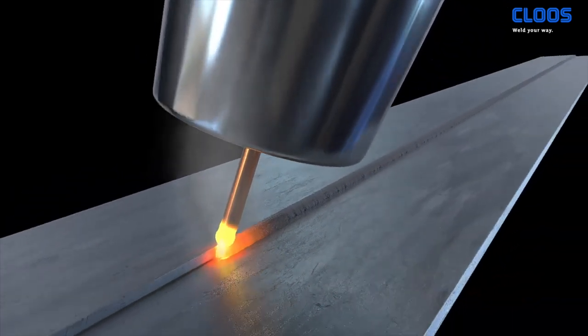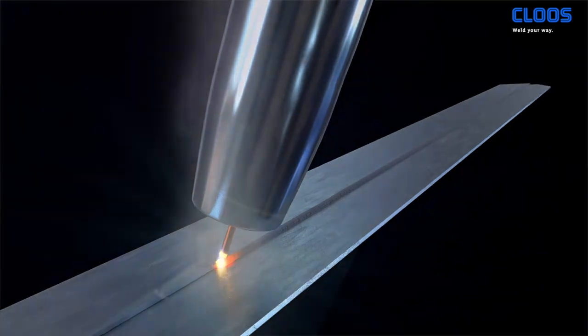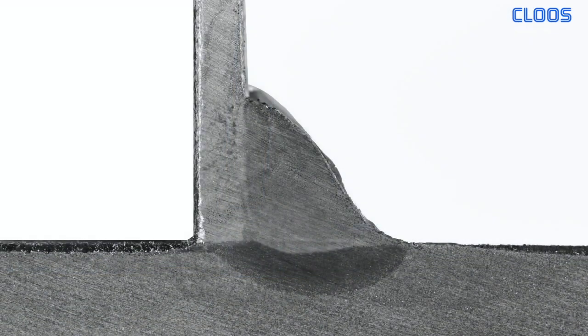The short circuit current, which is then significantly increased to generate the pinch effect, is very quickly reduced to low values again, shortly before the short circuit is resolved, that is, before the molten bridge is separated. As a result, the power in the newly ignited arc is kept low and the molten pool remains quieter due to the lower arc pressure. A short, uncritical current pulse afterwards ensures optimum drop formation at the end of the wire.